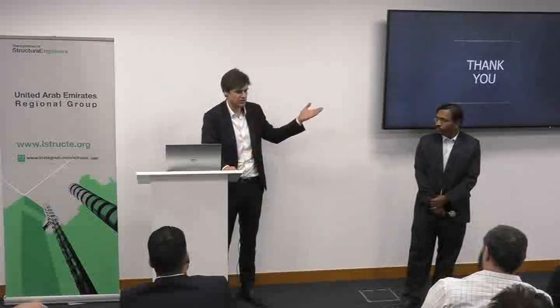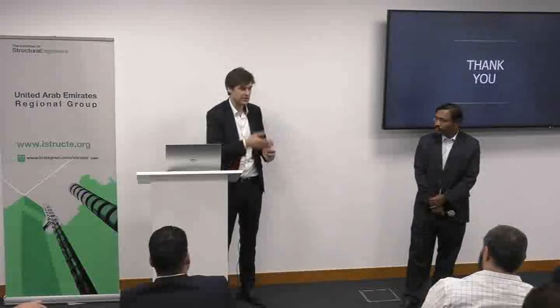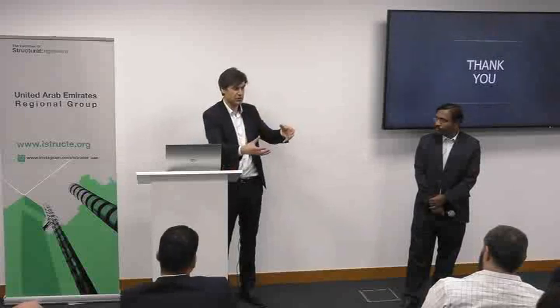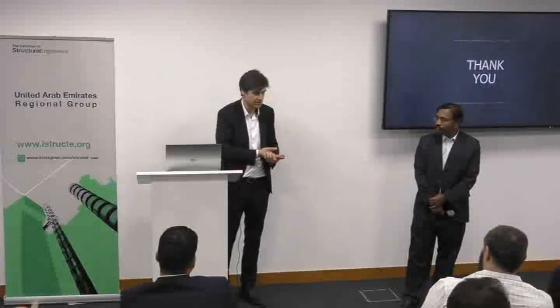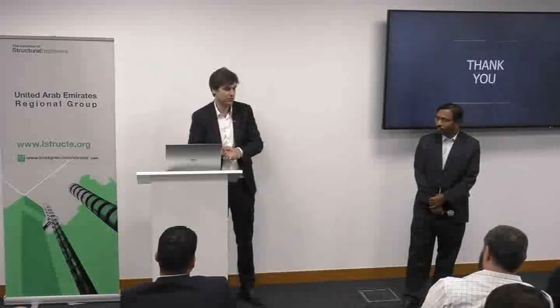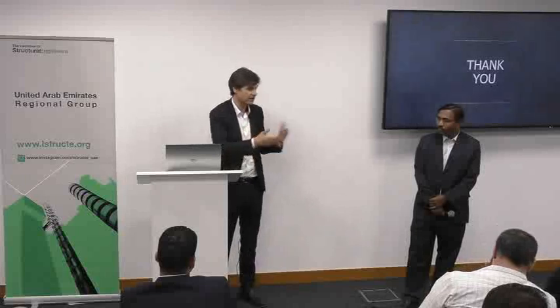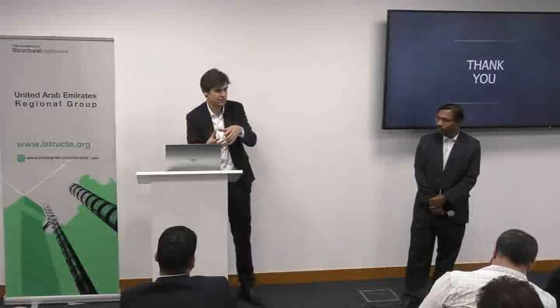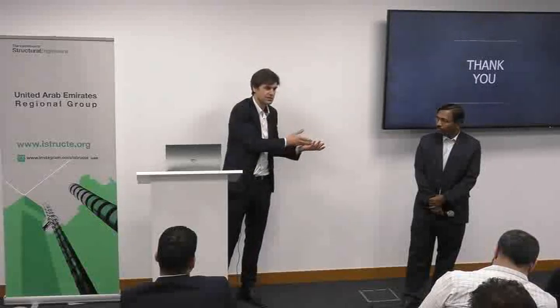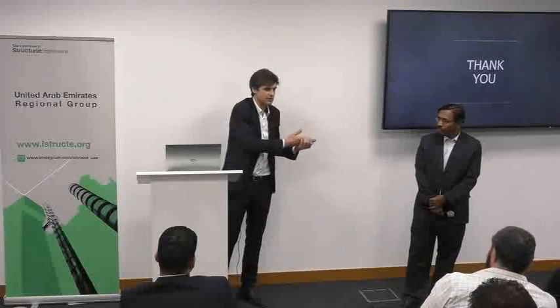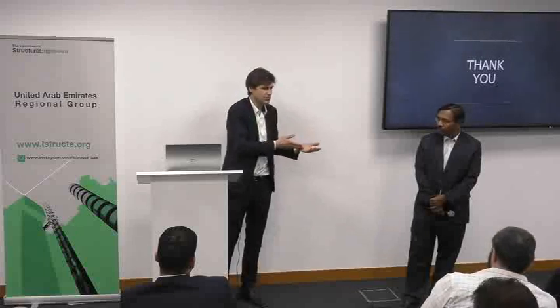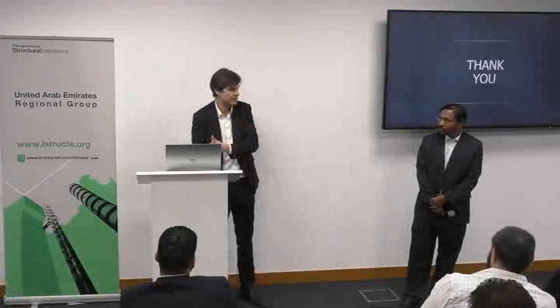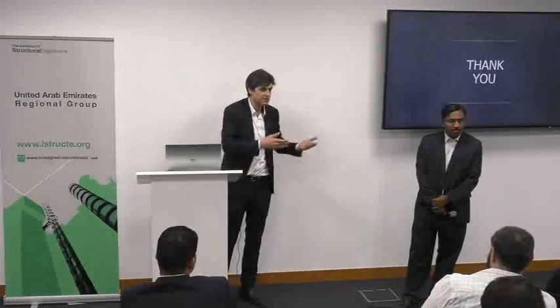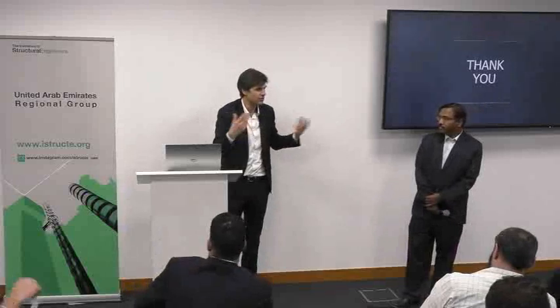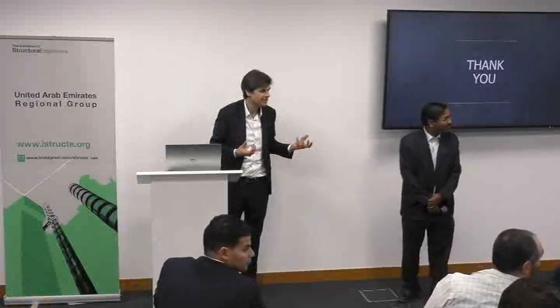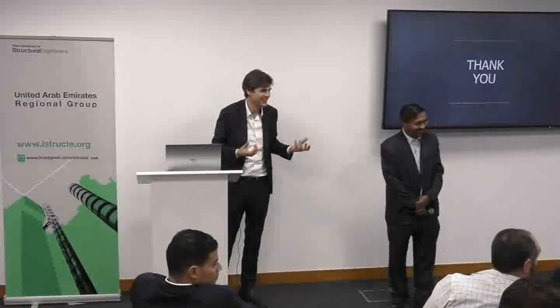And now there is one question about this super high grade strand. If you seek optimization as a designer by making use of this 2160 MPa grade strand, you have an optimum for your ULS verification and you are happy, but what happens with the fatigue? If you reduce the cross section, what is going to happen with the stress variation at the end? So of course, we have to apply a different rule. Today with the 1860, we have 200, and if you seek optimization by making use of 2160, maybe you would like to have a 250 MPa stress variation. And then you can have an equivalent optimization.